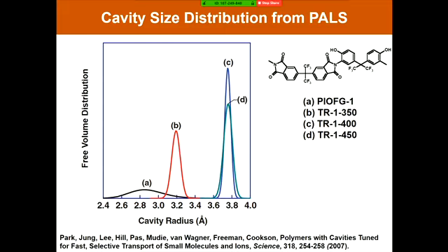as the polymer chains rearrange and the carbon dioxide from that reaction is released, it actually opens the structure of the polymer chains at a molecular level. And so you move this distribution to the right. The more open space you have in the polymer structure, the faster gas permeation can occur. And at the same time, it narrows the cavity size distribution, and that contributes to maintaining high selectivity while the permeability is increasing. Again, that's a combination that's not easy to do necessarily.